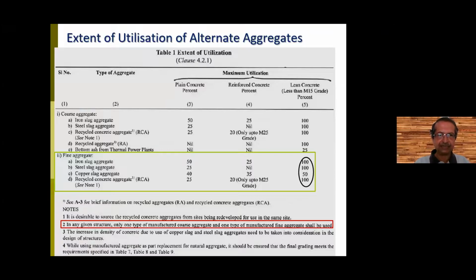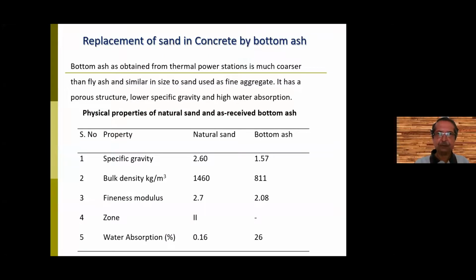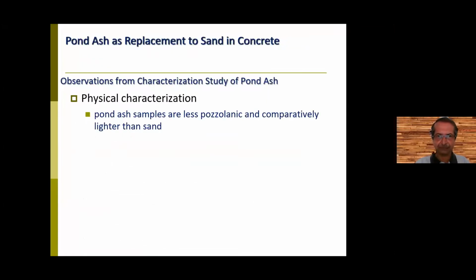So in any given structure, of course, the rule according to 383 is that only one type of manufactured coarse aggregate and one type of manufactured fine aggregate can be used. So people have tried to use aggregates, fine aggregates and coarse aggregates made from bottom ash. That is, in thermal power plants, after the burning of coal, you get bottom ash as well as fly ash. So people have tried using this and they have done the characterization of the natural sand and as-received bottom ash, which you can see here.